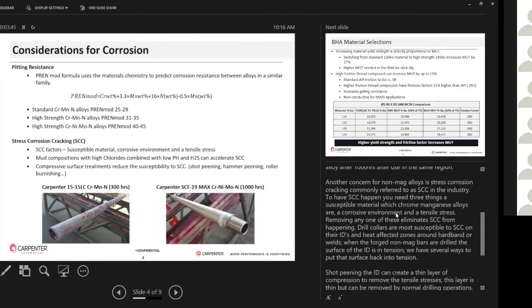Another concern for non-mag alloys is stress corrosion cracking. This is commonly referred to as SCC. To have SCC happen to your material, you need three things: material that's susceptible to it, a corrosive environment, and a tensile stress. So removing any one of those will eliminate SCC from happening. Drill collars are most susceptible to SCC on their IDs and heat affected zones around hard bands or welds.